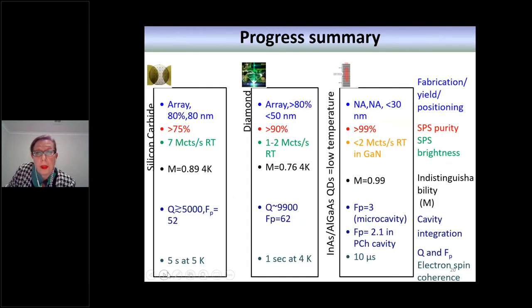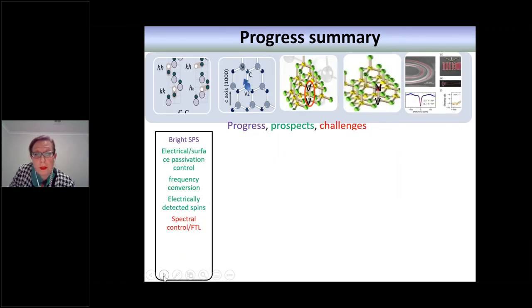And from the point of view of nonlinear photonics, it is quite good because there are already several devices that could permit frequency conversion of single photon sources. So if we look at a summary, the single photon sources in silicon carbide at room temperature are quite bright, and a good level of purity and indistinguishability has already been achieved. This is at 4 Kelvin, and definitely the integration in photonics is on par with diamond. Let's say that they're not as pure as the single photon sources in quantum dots. But there is an advantage, which is definitely the spin coherence time, which has reached 5 seconds at 5 Kelvin.